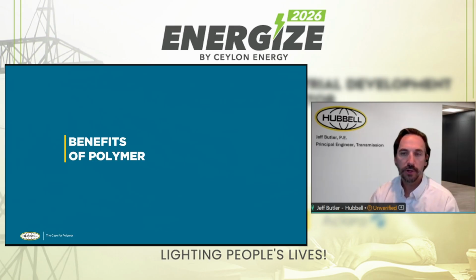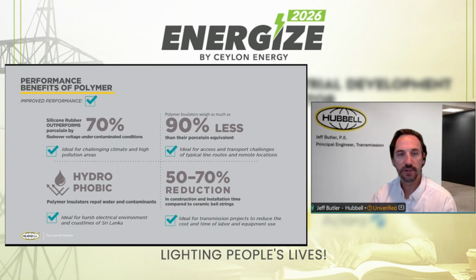So now let's talk a little bit about the benefits of polymer in general. So when we're looking at the use of polymer insulators versus ceramic insulators, porcelain or glass, I've alluded to it a little bit, but one of the key characteristics, as I mentioned, is that hydrophobicity, which is very effective in contaminated environments. So we saw a 30% reduction, 70% better performance than ceramic insulators when it came to flashover voltages in a contaminated environment.